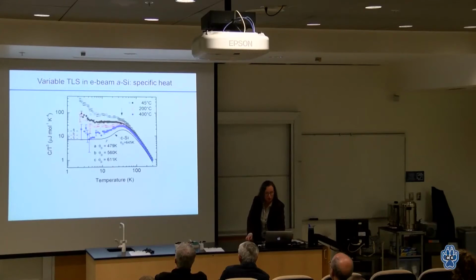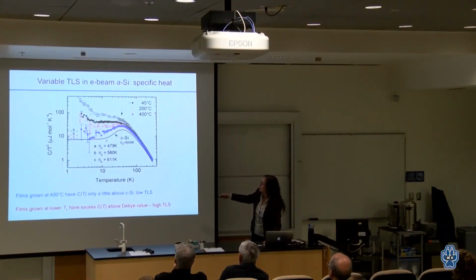Right? So we see that in our amorphous silicon. We see these big upturns. It depends on temperature, on the growth temperature, and various other variables. The high temperature films grown at 400 C have essentially none. The ones at lower temperatures have a lot.